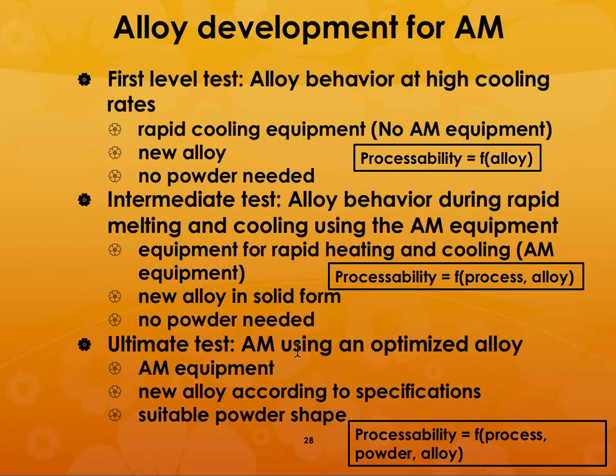So what are the steps in the alloy development? The first level test is you need to know what is the effect of the high cooling rate on the material. For that you don't need to take a powder itself. You can take a block of material and you need to have some kind of rapid cooling equipment. You heat it up and then you cool it at the rate at which you are going to cool during the AM process. So there the processability is only a function of the alloy.